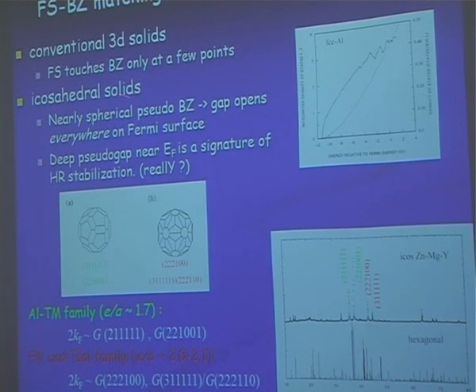But in the case of the icosahedral solids, we have the icosahedral distribution of the reciprocal lattice vectors, and we have a near spherical Brillouin zone. This is the typical X-ray diffraction pattern, with very strong diffraction peaks here, which is very hard to see, but it is indexed as 211111 and 221001.